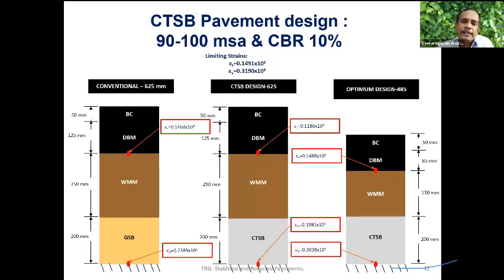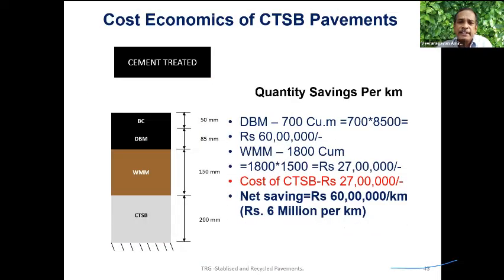This method of design is called a mechanistic empirical design, wherein I compute the stresses and strains of the pavement layers. I relate these strains to the performance in terms of rutting and cracking. There are allowable strain values. This again has to be cross-checked. Certainly, a 22% reduction in the thickness is possible.